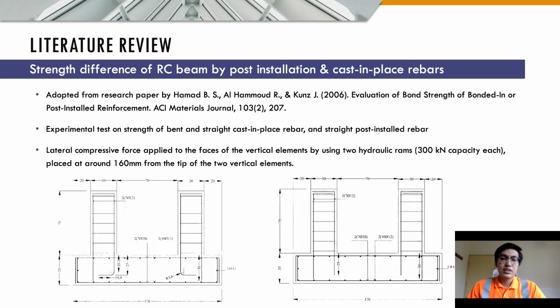The paper is about the experimental tests on the strength of bent and straight cast-in-place rebar and straight post-install rebar. The experiment was carried out by applying lateral compressive force to the faces of the vertical elements by using two hydraulic rams, that is 300 kN capacity each, and placed at around 160 mm from the tip of the two vertical elements. In this experiment, the vertical elements are acting as a beam, while the horizontal element is acting as